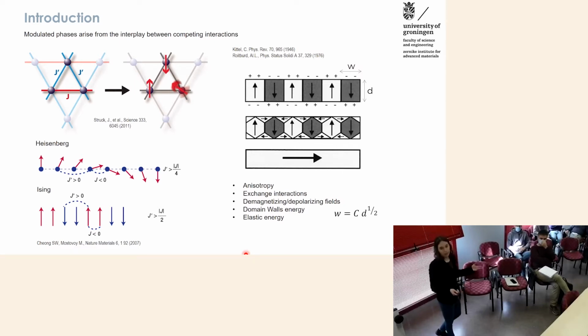And in the case of magnets and ferroelectrics, we have the demagnetizing and depolarizing fields, which will tend to break the system into domains. And then we have to consider the domain wall energy and the surface energy and the elastic energy. All these forces compete and bring different modulations and periodic structures in the system. In general, this was studied first by Landau and Lifshitz, and then Kittel and Roitburd also applied it to ferroelectric films. There are often laws which dictate the period of this modulated structure, and the period W usually scales with the square root of the thickness of the film, and this will come again later.